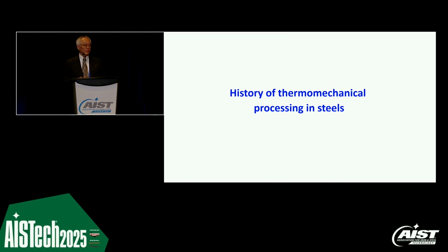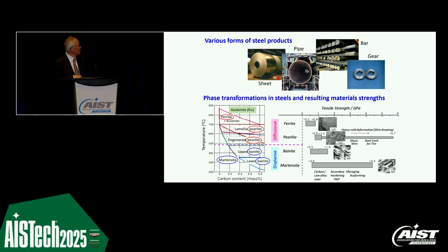So, the main topics. First, I'd like to mention the history of thermomechanical processing of steel. Of course, we know different kinds of steel products, from sheet, thick plate, and pipe, to bar and gear. To form these kinds of products, we use thermomechanical processing. Here I show you the different kinds of phase transformation products, I mean ferrite, pearlite, bainite, and martensite, placed on the phase diagram. This is the iron-carbon phase diagram, temperature versus carbon content. When you look from high temperature going down to low temperature, we have an increase in the tensile strength like this. So it is very important to control the transformation temperature to produce high strength steels.